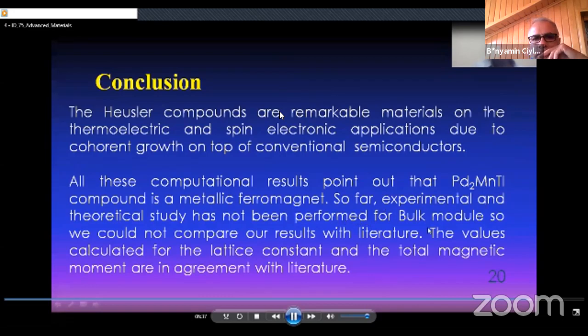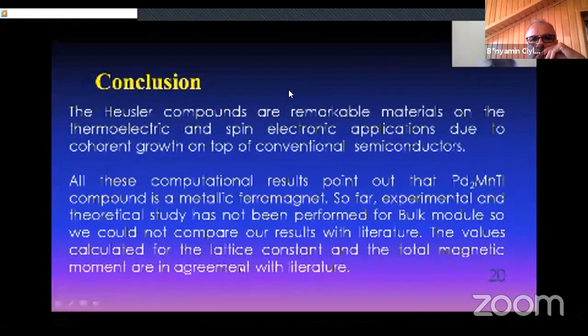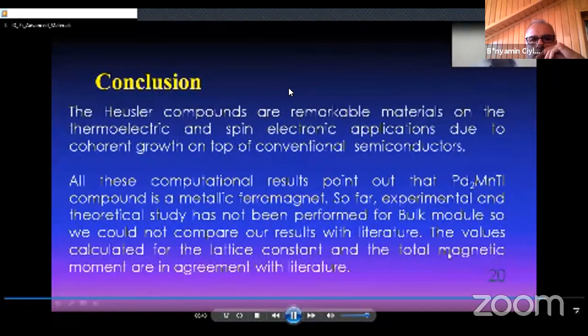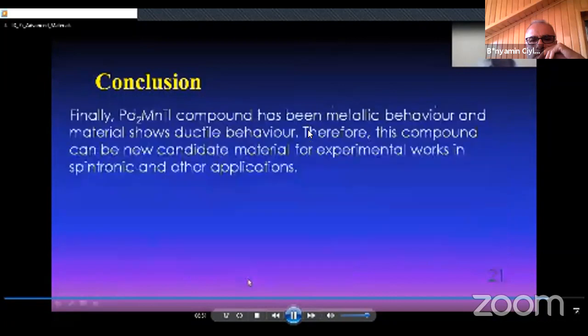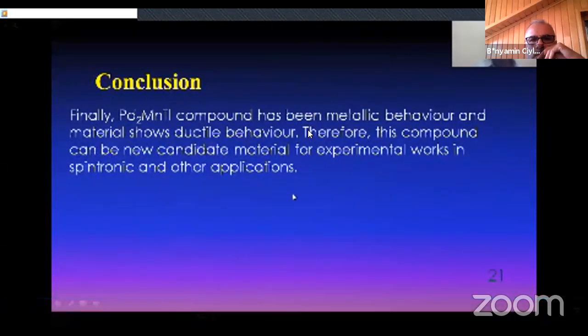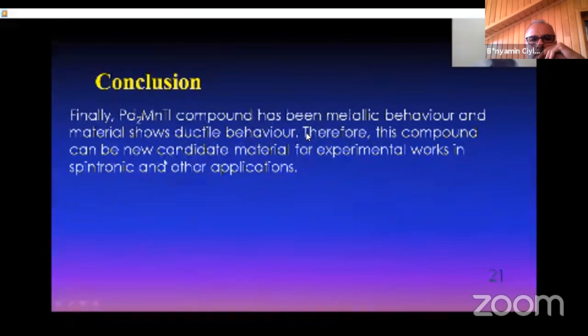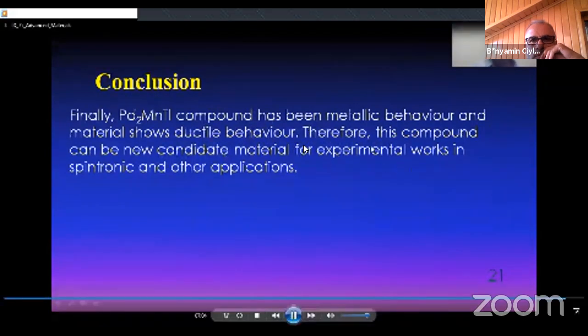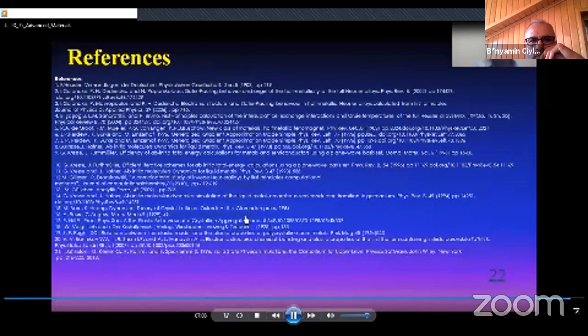So far, experimental and theoretical studies have not been performed for bulk modulus, so we could not compare all results with the literature. The values calculated for the lattice constant and total magnetic moment are in agreement with the literature. Finally, the palladium two manganese titanium compound has metallic behavior and the material shows ductile behavior. Therefore, this compound can be a candidate material for experimental works in spintronic and other applications.